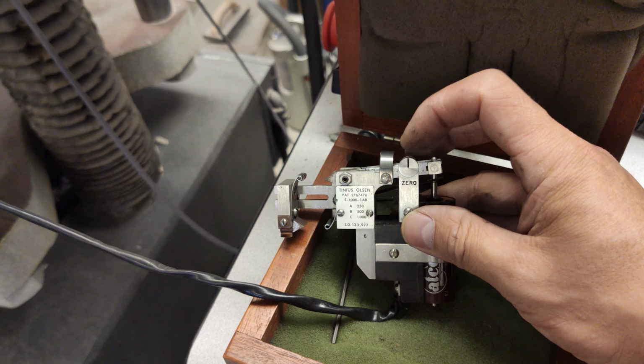Ladies and gentlemen, as you can see, Mr. Jadong San, the lab manager, is going to start the initial part of the experiment by measuring the area. Now, if we have a rectangular sample, we measure thickness and width. For a cylindrical sample, you measure the diameter, or 2 times the radius. And you take a couple of readings, 3 readings, and you average them. And the number is about 0.498. Yeah, about half an inch.